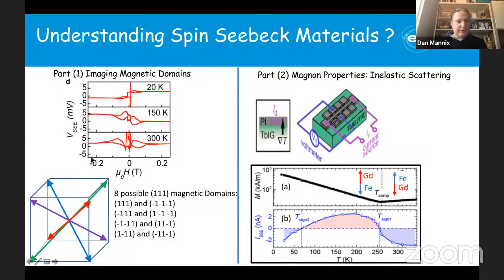So this is what we wanted to address. We wanted to see if there was some kind of magnetic texture inside the materials that was actually inhibiting the efficiency of thermoelectric generation. And in these materials, the magnetic moments are oriented along the 1-1-1 direction of a cube. There are basically 4 equivalent 1-1-1 directions of a cube, which can give rise to essentially 8 in principle magnetic domains.